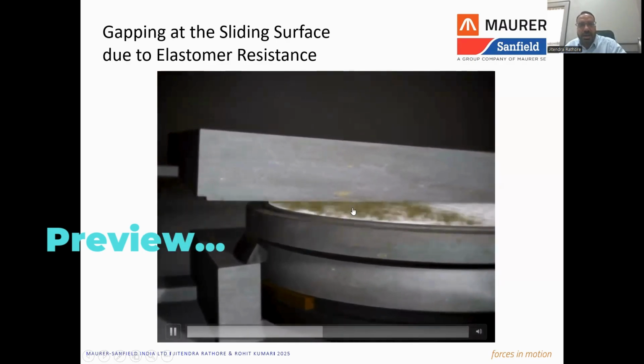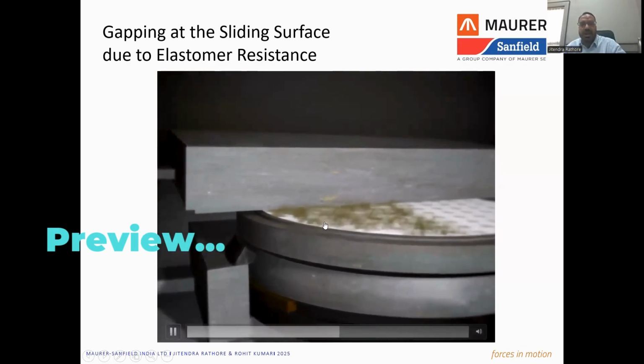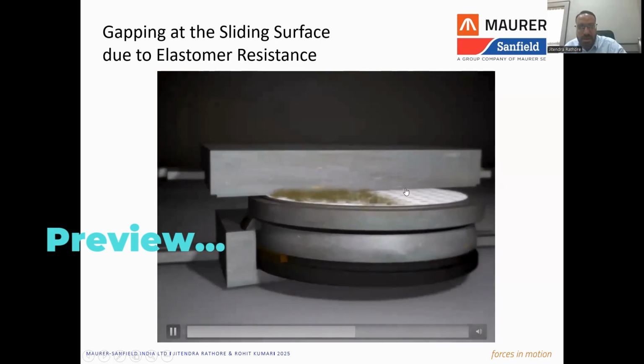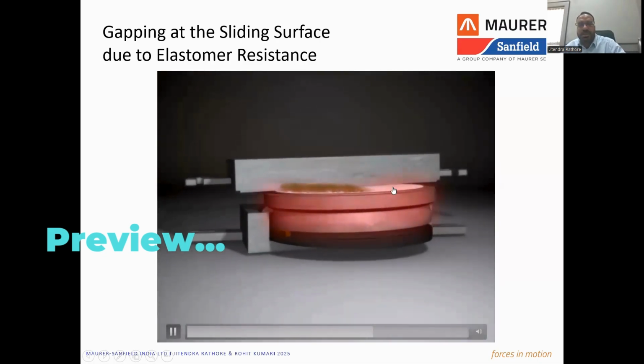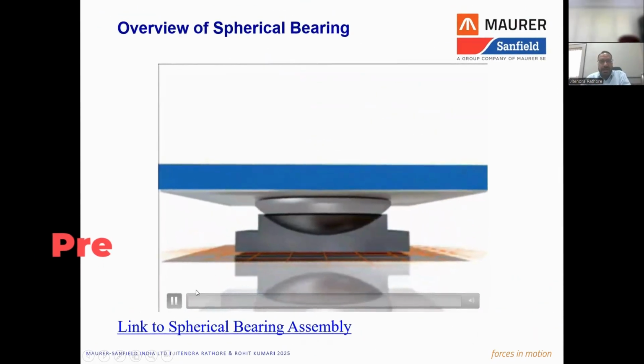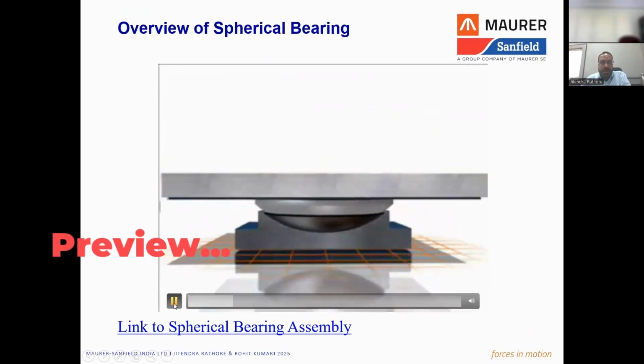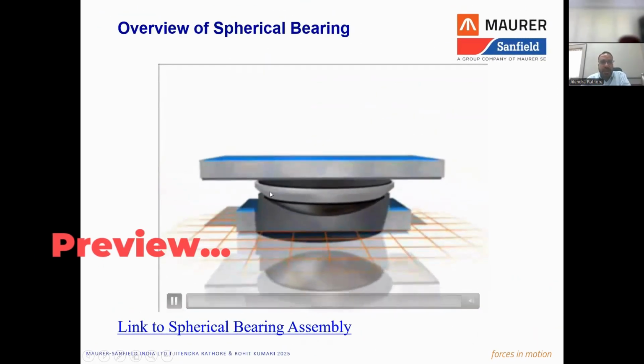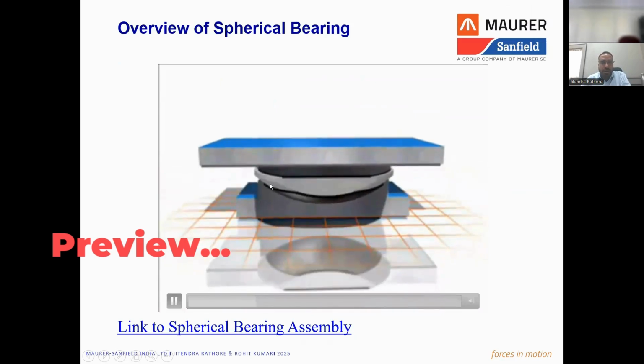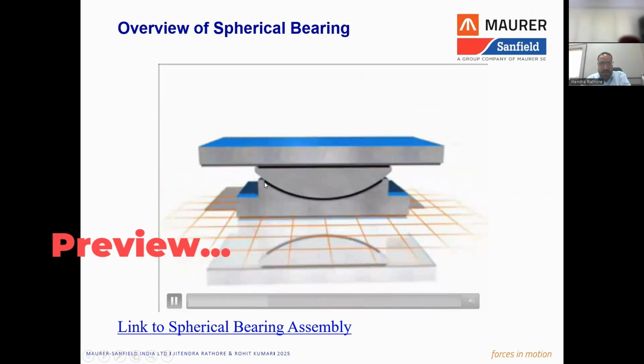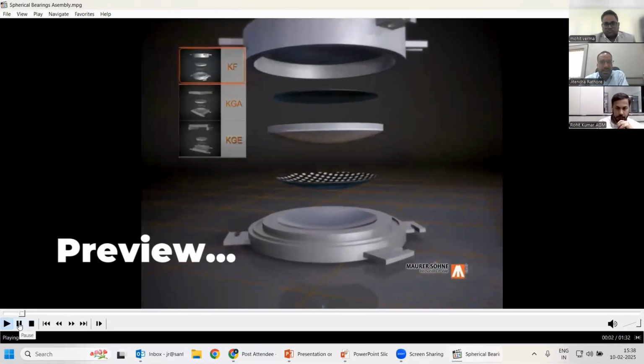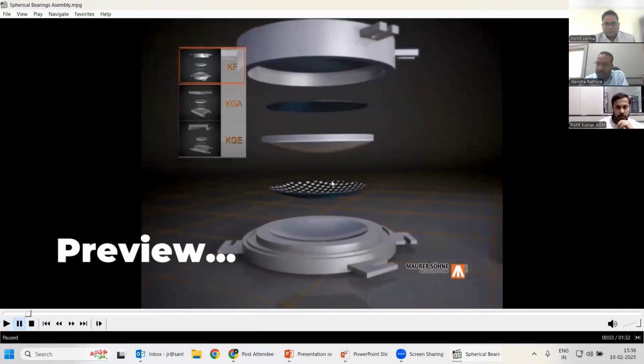This material or this area of the sliding material can get contamination also, whereas due to the extreme concentration of load on the other end, unlike the PTFE bearings, in a spherical bearing, we have an interface of concave and convex components, and there is a lining of low friction material in between. This is a fixed spherical bearing.